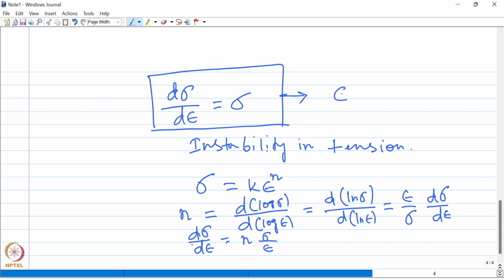Okay, so the true uniform strain epsilon u is nothing but the strain up to the maximum load. So if we put this over here, we will get the true uniform strain at which the necking begins is equal to the strain hardening exponent n. Okay, so this is an interesting relationship. So when the strain hardening exponent becomes equal to the uniform true strain in the material, the instability in tension starts, or in other words, the necking will begin.